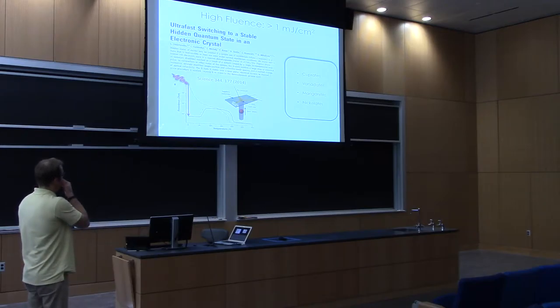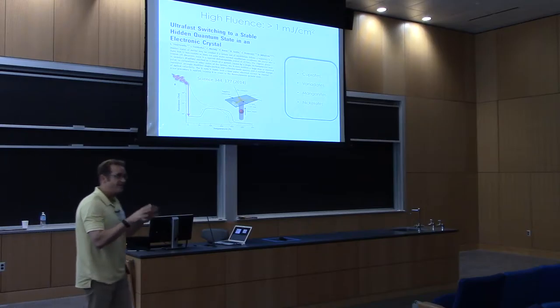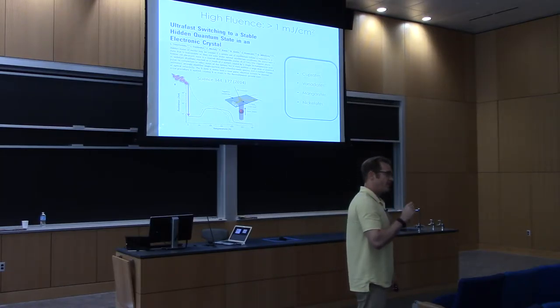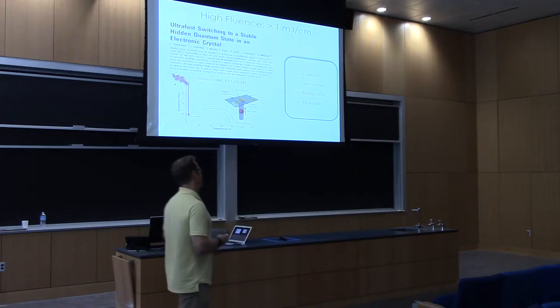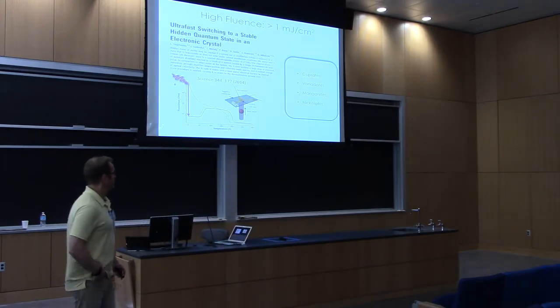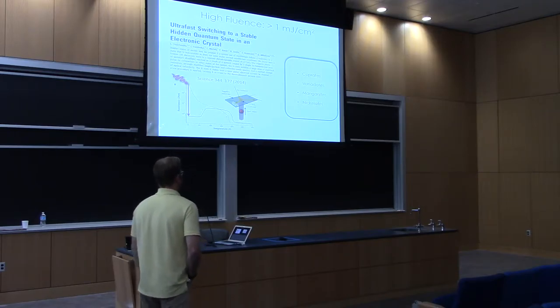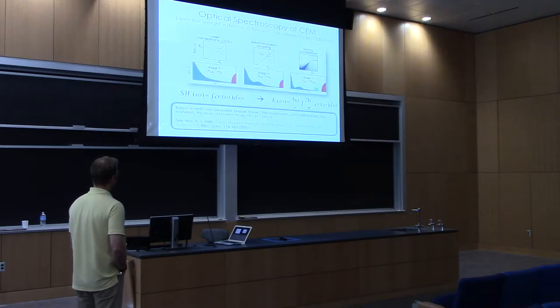I'll just give you a couple of examples of this. Here's a really nice example on 1T-TaS2. The reason I'm showing you this is because it's a really nice example where they came with about a one millijoule pulse at low temperatures. And they have a change in conductivity and their resistance decreases by more than three orders of magnitude. And this is metastable. This stays. This persists until you increase the temperature back and bring it back to the insulating phase. The reason I bring this one up is because, as far as I know, there's two examples where, two materials where this happens. One is this 1T-TaS2. And the other one is the one that I'm going to show you in a few minutes on this lanthanum calcium, the strained lanthanum calcium. So this is a really neat example of the sorts of things that people are trying to do. There's also many experiments of this flavor on cuprates, manganates, and nickelates, looking at trying to melt, for example, charge order, and obtain a superconducting phase, or just looking at the dynamics of the melt.